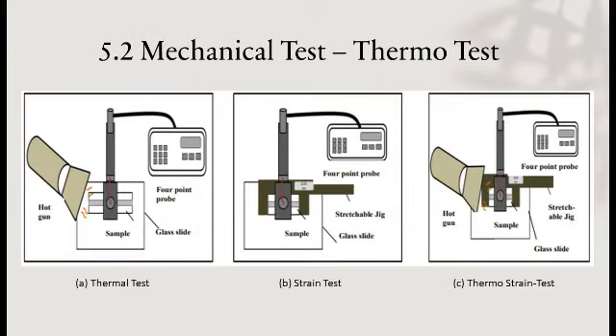For the thermal test in figure A, the conductive ink sample is heated from low temperature, then intermediate temperature and high temperature, for 30 seconds. Then the sheet resistance was measured using a 4-point probe, as in the picture before. That is the 4-point probe, and the reference point for the thermal test is the room temperature, which is 22 degrees Celsius.